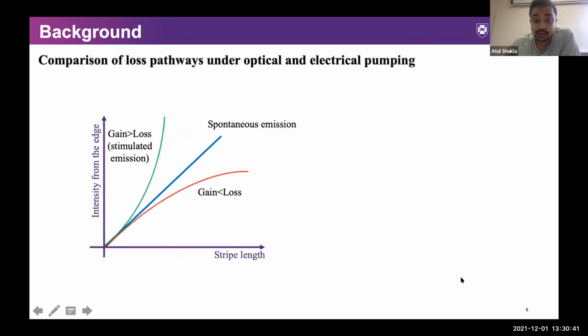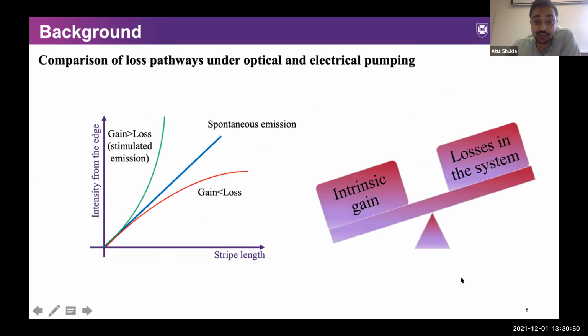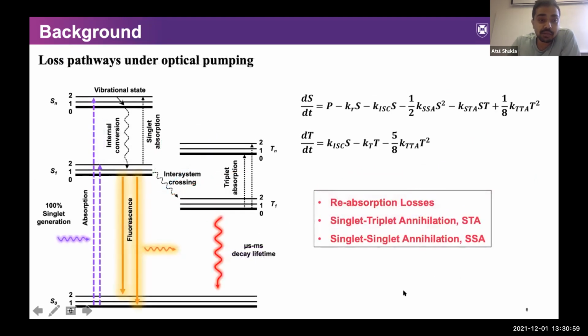Now, talking about intrinsic gain, we also have losses in our system. In order to have net positive gain, we need intrinsic gains higher than the losses in the system. So let's look at how the losses originate. Under optical pumping, 100% of the excitons generated are singlet excitons, and triplet excitons are generated through intersystem crossing. The main pathway of loss in this system is reabsorption losses. There are also singlet-triplet annihilation and singlet-singlet annihilation losses,